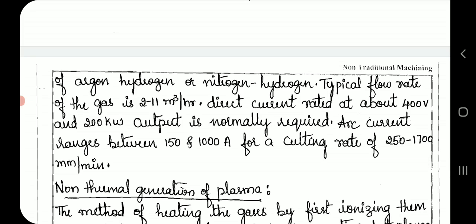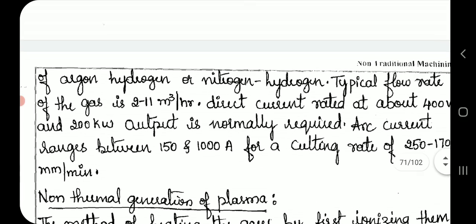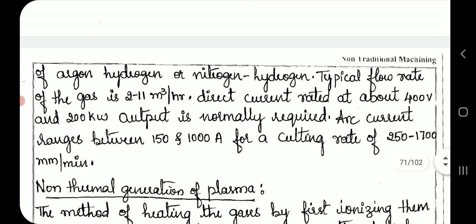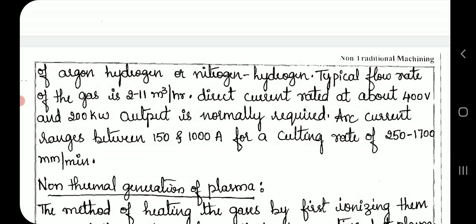Typical flow rate of the gas is 2 to 11 cubic meters per hour. Direct current rated at about 400 volts and 200 kilowatt output is normally required. Arc current ranges between 150 and 1000 amperes for a cutting rate of 250 to 1700 millimeters per minute.